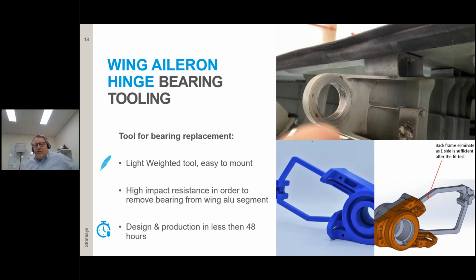This is a nice example from aviation. It is an aileron hinge bearing tooling. You see the hinge bearing tooling, which is normally having a metal bearing inside. And the customer required a tool to remove this bearing from the aluminum part without damaging the aluminum part. And the 3D printing was able to print a very simple tool, put it around the aluminum aileron part, and hammer out with an additional nylon carbon fiber 12 tool the bearing from the part and replace it with a new one. Fantastic example. It is very lightweight. It addresses all the important ergonomics. And if I remember correctly, the tool was around 1,200 Australian dollars, and it was delivered within 48 hours. Very straightforward.